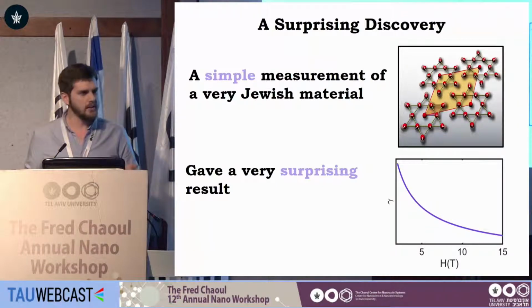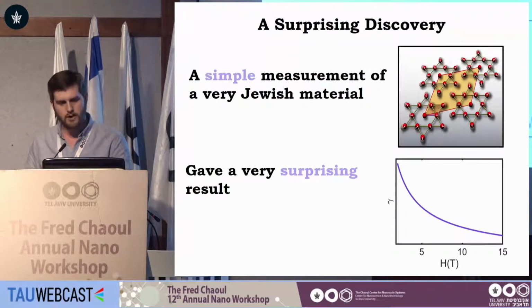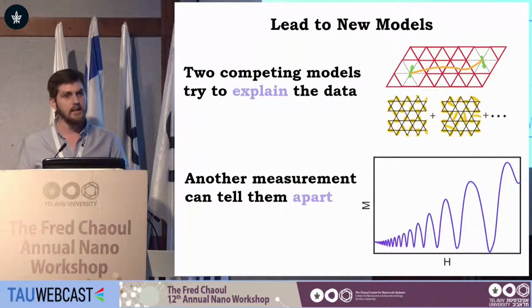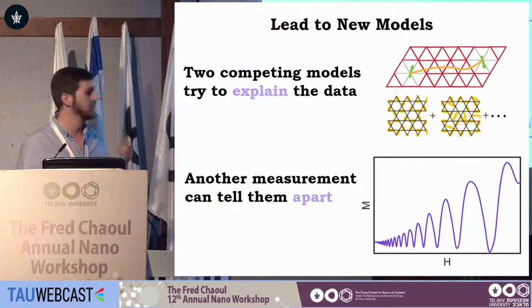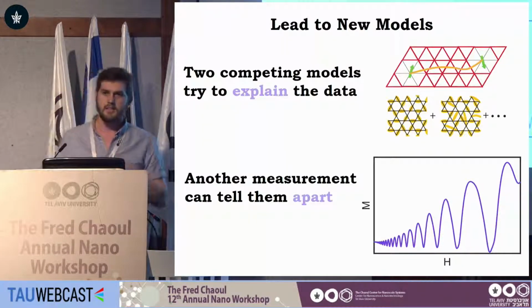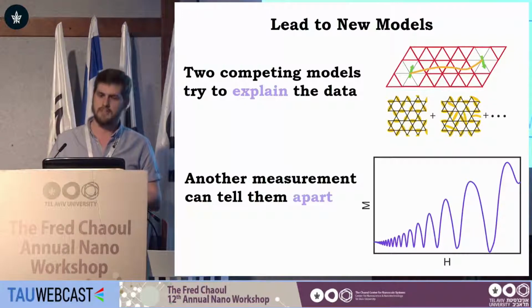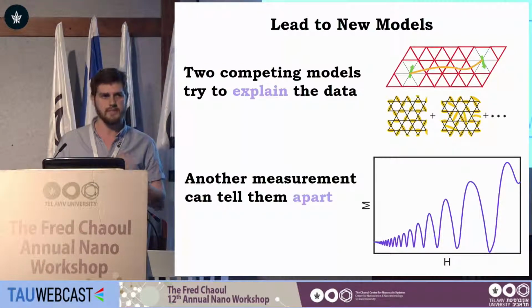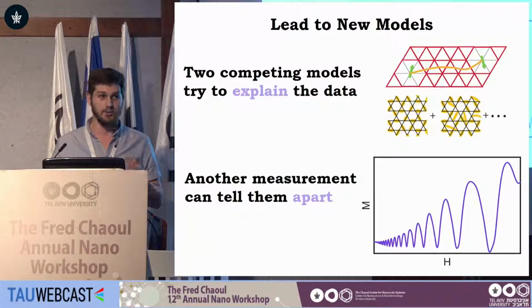So this unusual result led to two models trying to describe that data. Those two models really describe the data well, but have very different predictions regarding the magnetization of the material. So the next step is to measure its magnetization and try to differentiate if this material is really the quantum spin liquid I'm looking for.